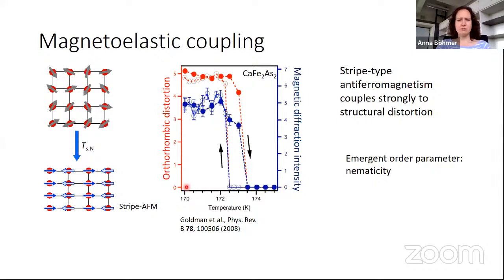So here is a function of temperature. We look at basically how much magnetic order there is in blue, and how much this deviates from being square in red, and that just goes hand in hand. So we find a strong coupling between this sort of antiferromagnetism and a structural distortion from square. This goes with what's called an emergent order parameter, and that's going to be at the end of my talk. I hope I can explain this interesting concept of solid-state physics.